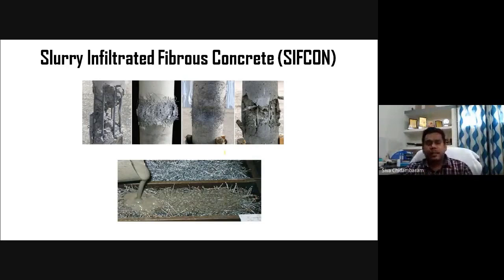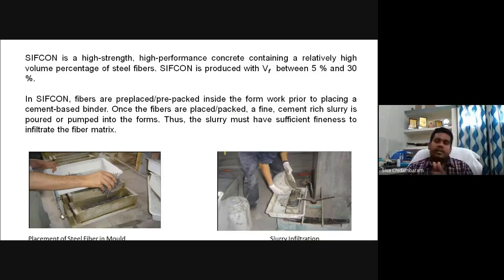So it has a lot of restrictions, like the formwork should be plug free, it should be leak free, number one. So a perfectly made formwork, number one. We should not use a compact vibrator to vibrate this. A perfect small amount of vibration has to be done. If your slurry is infiltrated improperly, slurry is the backbone of your SIFCON, so if it is improperly infiltrated, then you can't attain the desired performance. So there are a lot of limitations.